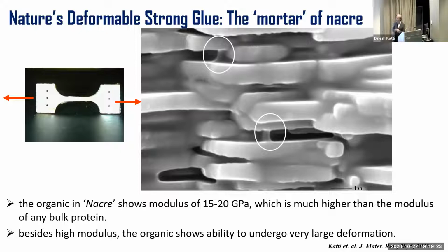But here what we found is that not only is that organic mortar very stiff, but it can also deform a lot. It can stretch a lot. And that was a fairly unique property here. And so we decided to investigate this further. Why is it that this is happening?